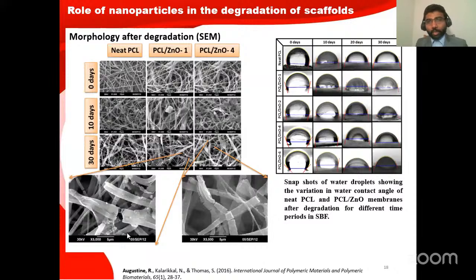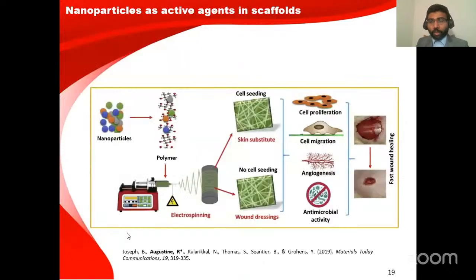As you can see on the right side, the hydrophilicity of the scaffolds increased over time, especially when the zinc oxide nanoparticles are there, because the degradation of the scaffolds exposes hydroxyl and carboxylate groups, which are hydrophilic in nature, and so the hydrophilicity of the material increased. So nanoparticles can be used as active ingredients in the scaffold as well. For example, we used several metal oxide nanoparticles, especially zinc oxide, cerium oxide, titanium dioxide, yttrium oxide, to improve the biological performance by using them as active agents.